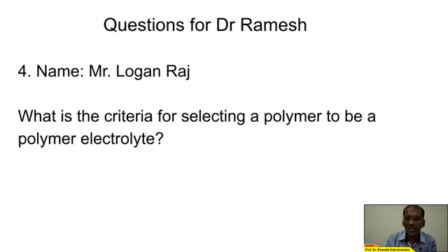So what they're trying to say is the main conductor in lithium-ion batteries is the lithium ion. For the lithium ion to be a conductor and to do the hopping mechanism based on the Arrhenius theory, there must be some kind of electronegative element in the polymer backbone. So for us to select a polymer to be used as a polymer electrolyte, there must be an electronegative element. So in polymethyl methacrylate, there is oxygen due to the ester functional group.